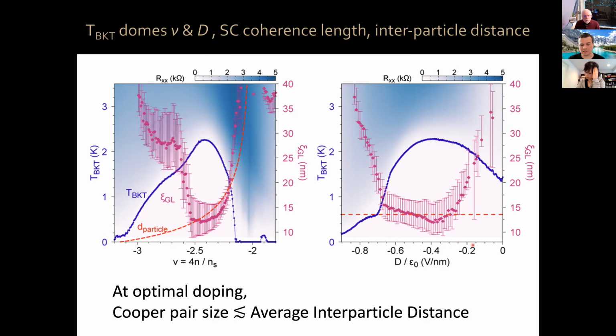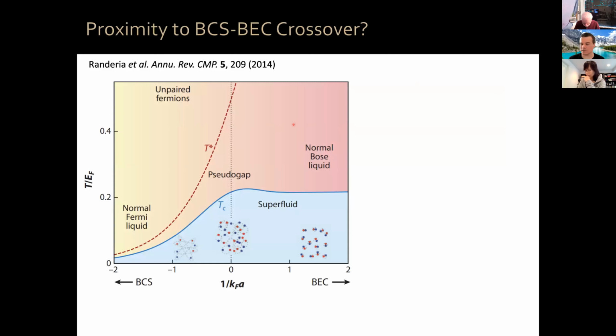So this is reminiscent of the situation that occurs in cold atoms, where you have a BCS to BEC crossover. This picture is from the review by Randeria and Taylor, where in the cold atoms community you have this tunable knob, the Feshbach resonance, that allows you to tune the interaction strength such that you go all the way from the BCS limit, where your Cooper pairs are very large compared to the average interparticle distance, all the way to the extreme BEC limit, where you have tightly bound pairs of fermions, which are very diluted. Their distance is much closer than the average interparticle distance, and the BCS to BEC crossover occurs roughly when the Cooper pair size is of order the interparticle distance.